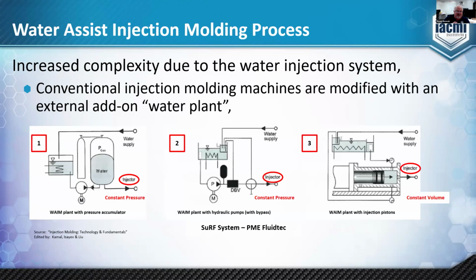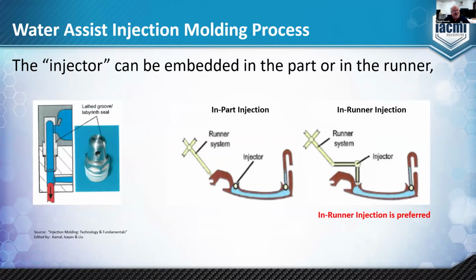The complexity comes in the water injection systems, which come in a variety of configurations that deliver the water either at constant pressure or at constant volume. In constant pressure, you have two types of systems, one that uses an accumulator and another that uses hydraulic pumps. In the constant volume system, you essentially have a hydraulic cylinder that will deliver a set volume of water to the injectors. Each of the systems delivers water to an injector. The injector could be a nozzle, either located in the runner system or in the part itself. The nozzle can be rotated to shut the water on and off, or the nozzle could essentially be a pull pin, where you pull the pin to release the water and you re-engage the pin to shut the water down. It is preferred to place the water injector in the runner system so that you minimize the cosmetic defects to the part surface, particularly if you're going for a Class A finish.